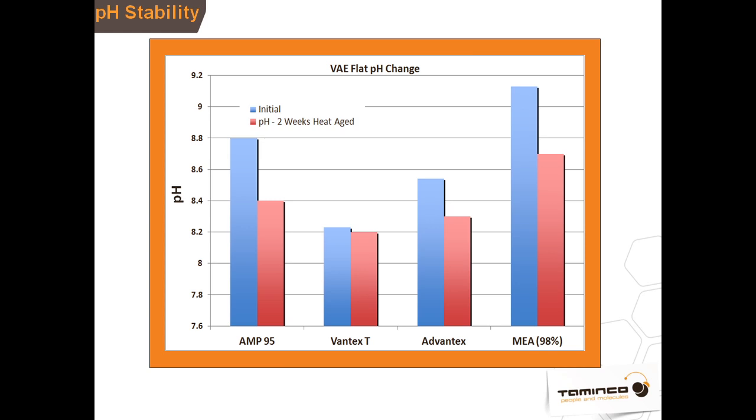These other alkanolamines are caustic with very high pKa. Once you set their pH at, I'm going to say 9, which is below their pKa, once acid starts to be generated in those paints, they are already below their buffer range. So you get much greater changes in pH per milliequivalent of acid generated in a given system. So this was something that we observed as we ran a bunch of these comparative paint studies, and it's one example of a benefit that you can get by looking at alternative structures for the various additives that you're using in paint.